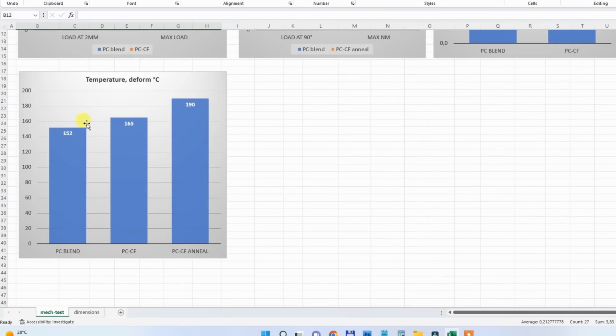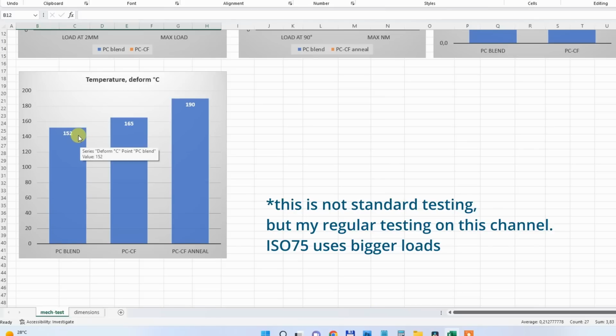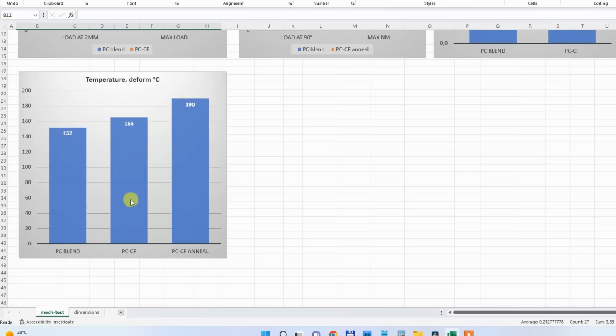And the temperature test, basically all 3 materials are great in this test. The PC blend, I noticed the first deformation at approximately 150 degrees Celsius, but it was very hard to notice this even when analyzing the time lapse frame by frame. Very similar to carbon fiber, and of course the best was the annealed version.